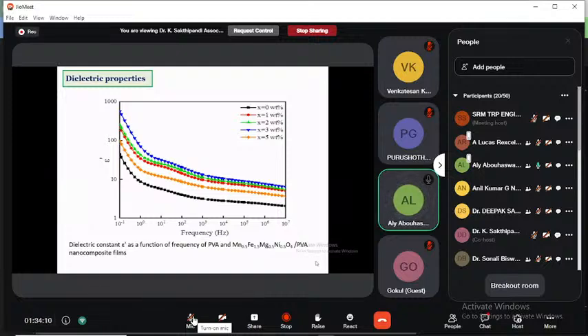As seen from this figure, we found that as the frequency increased, the permittivity of the sample decreased. But as we increased the nanofiller material, we found that the permittivity of the sample increased with increasing the nanofiller.